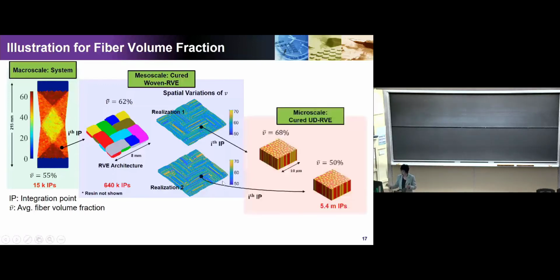Okay? And if you do one more expansion, that will be the microscale level simulation. Now you can see each point is a cross section. You can see thousands of fibers there. And those fibers have angles, have misalignment that you have to take into account. And in this different realization, you can see that their volume fraction is also different. I'm just using volume fraction as one example of a random variable, but in our problem, we actually have the misalignment angles, two angles, that we take into account. And they are coupled. There's some coupling between them and the volume fractions.